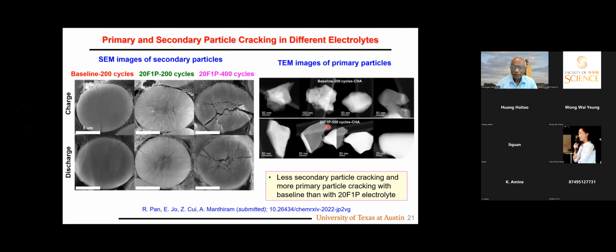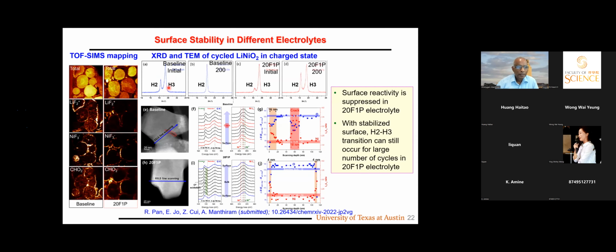So if you look at the TEM, in the baseline electrolyte, you can see small micro cracks in the primary particles. In the other electrolyte, 20 F1P with the FEC, we don't seem to see much primary particle crack at all. So it turns out in LP57 conventional electrolyte, more secondary particle cracking, there is aggressive surface reaction. That's why this happens. Here, less surface reaction, and therefore we don't have much primary particle cracking. And then why is the secondary particle cracking? You can look at the X-ray peaks again.